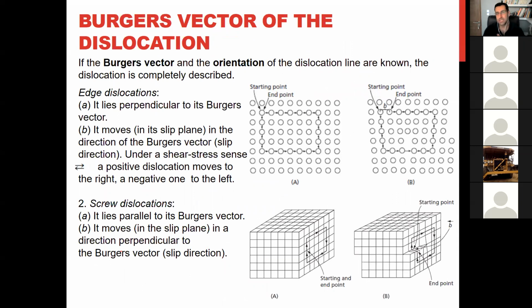To talk about dislocations, you have to define them. We define dislocation by Burgers vector and orientation. And Burgers vector is something easy. For example, if you have a perfect crystal without defect, without dislocation, if you start from one atom and you make a loop, you reach this atom. But when you have a dislocation here, if you start from this atom, you will not reach the origin. So this is a Burgers vector.